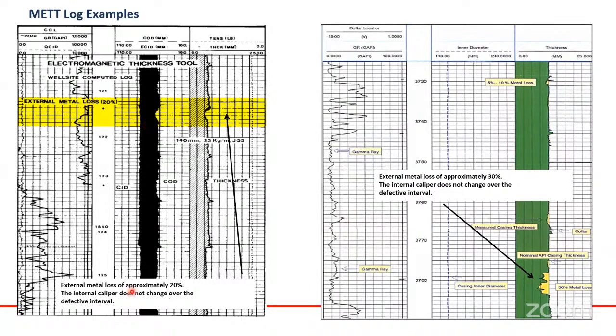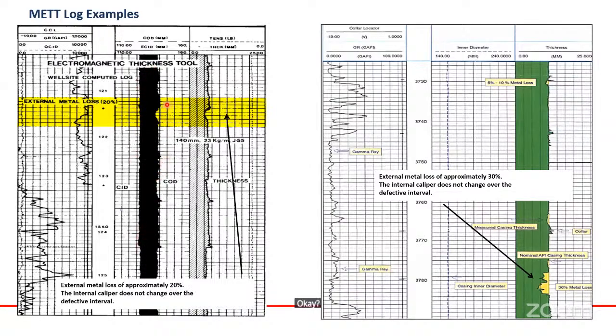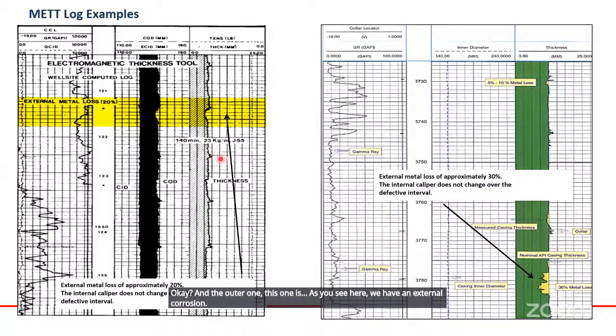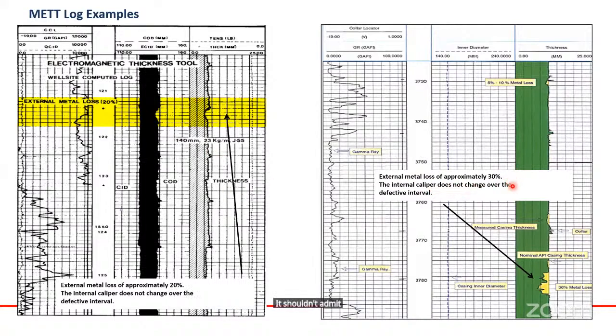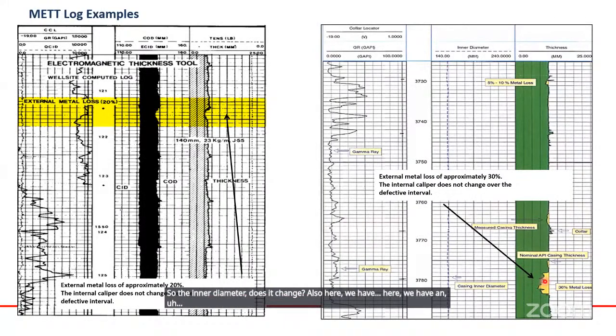So, external metal loss. This is another example of the METT. External metal loss of approximately 20% here. The internal caliper does not change over the defect, which means that it's external. Here is the caliper, as you see. And the outer one, as you see, has an external corrosion. External metal loss of approximately 30%, as you see here. The internal caliper does not change over the defect. So the inner diameter doesn't change. Also here we have a metal loss of about 30%.